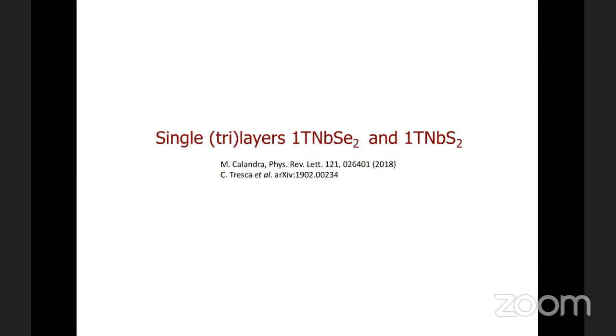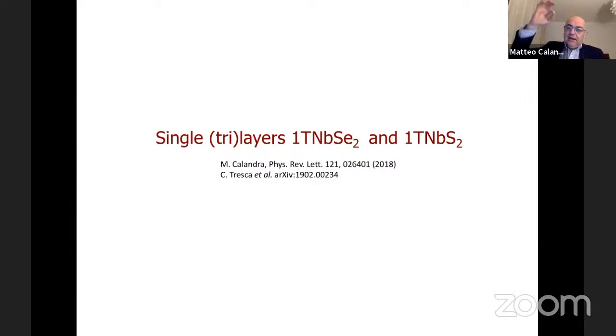Yeah, so essentially you have two ways in which you can look at the occurrence of a charge density wave transition. One is that you look at the gain of free energy between the low T phase and the high T phase. If you have a first order transition, you just look at the difference between the free energy of the high T phase and the low T phase. If you have a second order transition, you can also look at the high T phase and see at which temperature the phonon becomes imaginary. Why? Because you can think in terms of Landau theory.